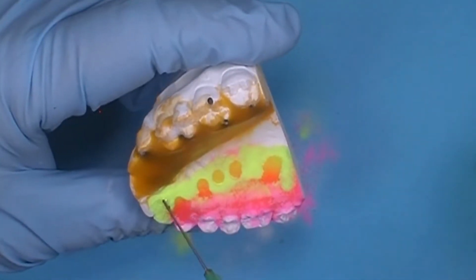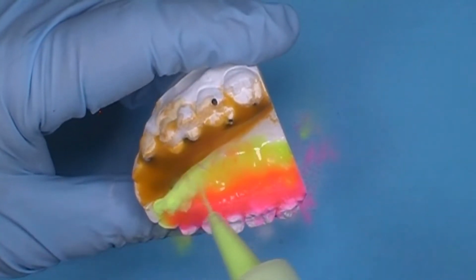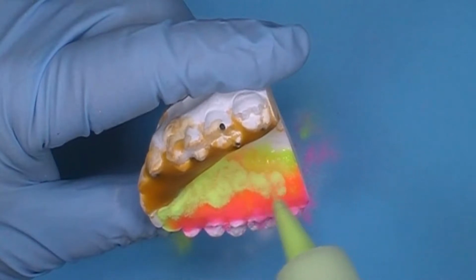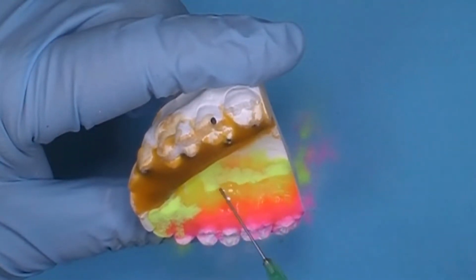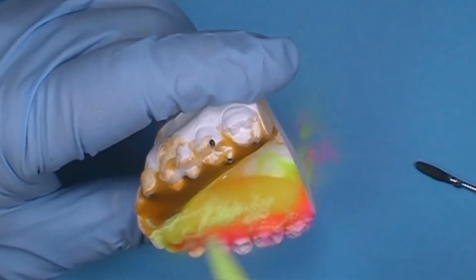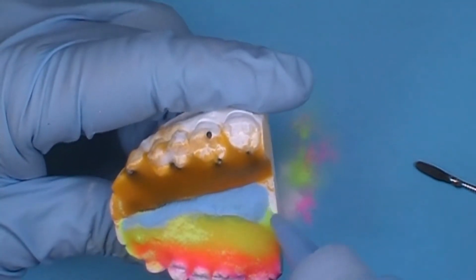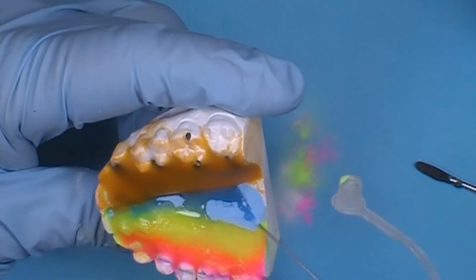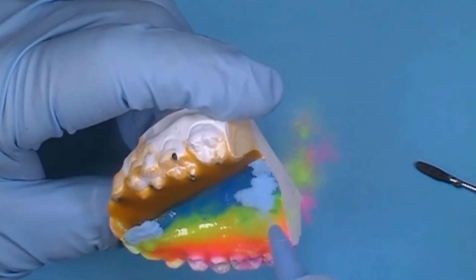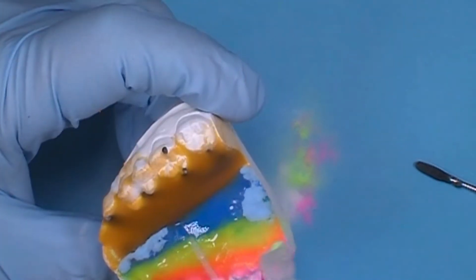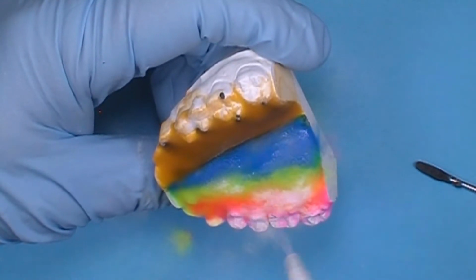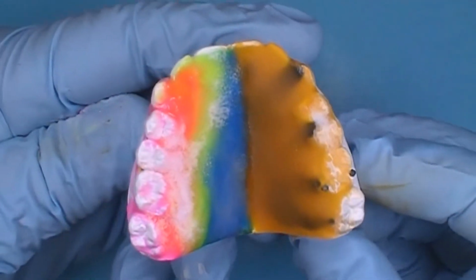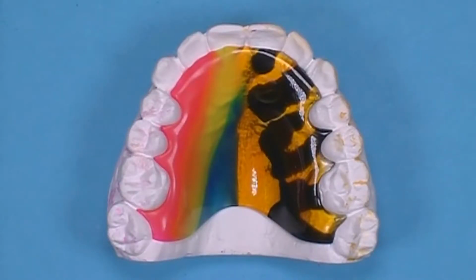Colors can be clear polymer powder with colored monomer dyes or colored polymer with clear monomer. Here, Tropical Tones acrylic resin is being used. Before placing applied acrylic into Great Lakes pressure pot, dust a small layer of clear polymer powder to thicken, mix, preventing slumping. Cure in humid pressure pot for 15 minutes. Once cure is complete, remove model from pressure pot, then trim and finish appliance.